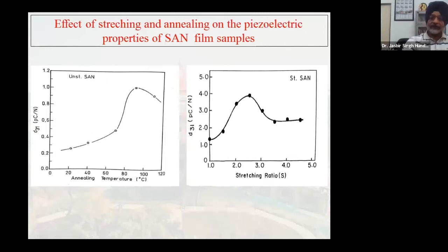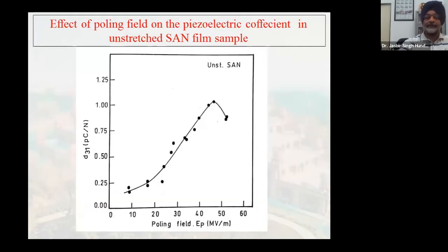Okay, and as I told you, when the stretching ratio is big, the chances of electric breakdown of the film increase. As you saw in the picture, when chains are moving apart, the chances of electric breakdown increase. So stretching the film to a very high ratio is damaging for the film. But a stretching ratio of 2.5 times, that is, if a 1 centimeter long film is stretched to 2.5 centimeters, that is the stretching. But a stretching ratio beyond 2.5 seems to affect D31 adversely.